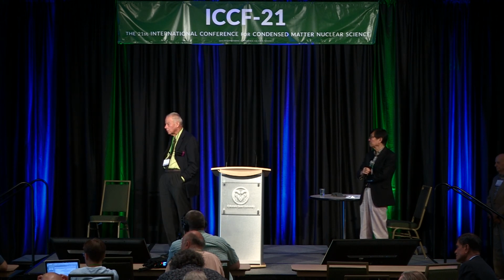Right. Well, palladium-boron has to be made in an exact way, and Dr. Imam made it in a certain way. For one thing, you have to reproduce exactly how he made the palladium-boron to get the same effect, I think. And also, everybody doesn't set up experiments the same as I do. You know, how you polish the electrode, what you do before the experiment, how careful you are to keep water contamination out of the system. There's a lot of variables during the preparation as well, and those have to be made the same in order to get the same results.